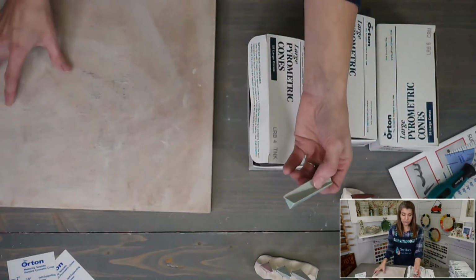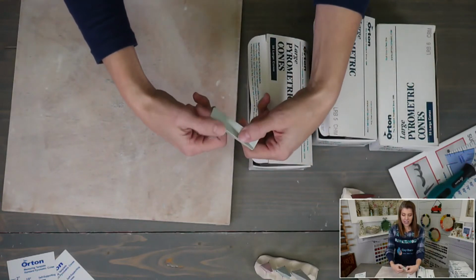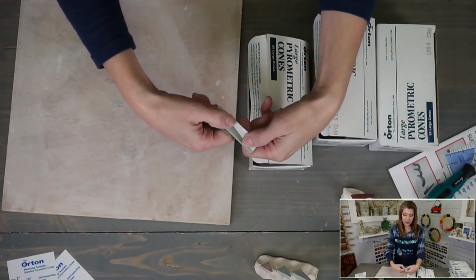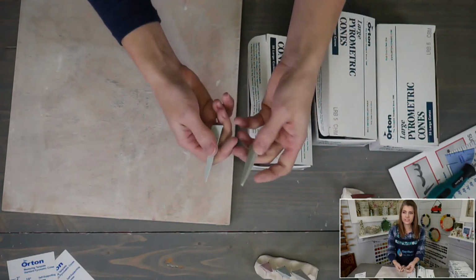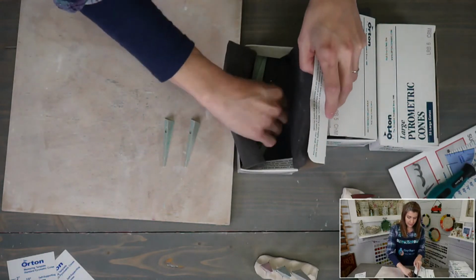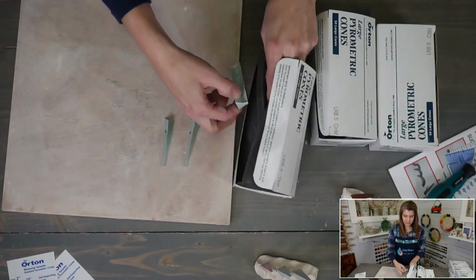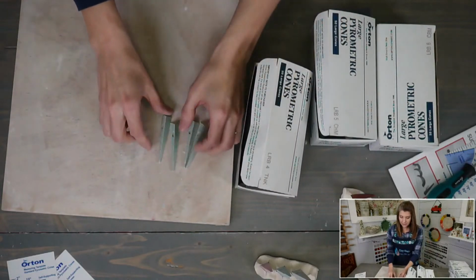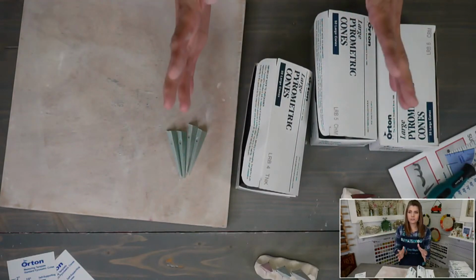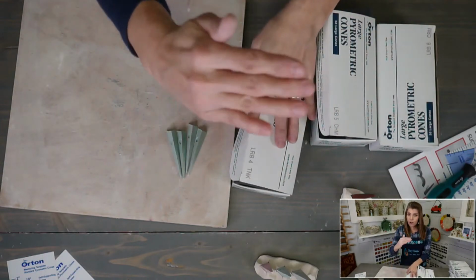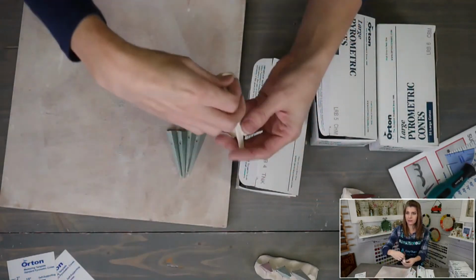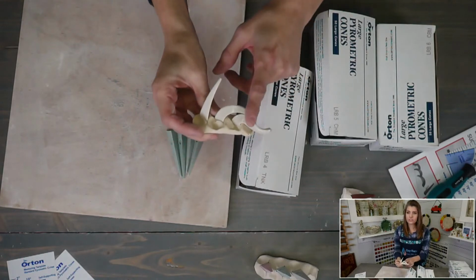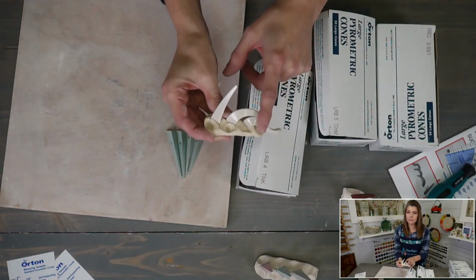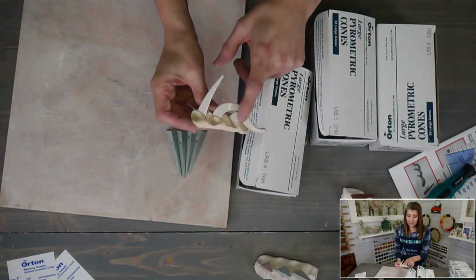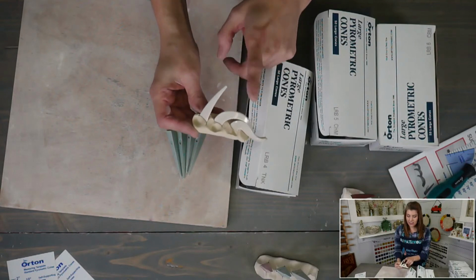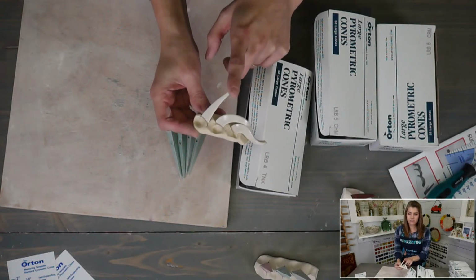Okay, so here's the cone 4s, right? And this is how I break them. I hold them each by the fatter part and I just pull down. See how they snapped apart? So that's the 4s. So let's get a couple out. So this is how I make them. So when we think about melting, what's going to melt first? The cone 4 is going to melt. So let's look at our cone pack. The cone 4 is the coolest temperature. That will melt first, so that has to be at the back. The cone 5 is our middle, that's our target cone, and then cone 6 is the hotter, so we put that at the front.